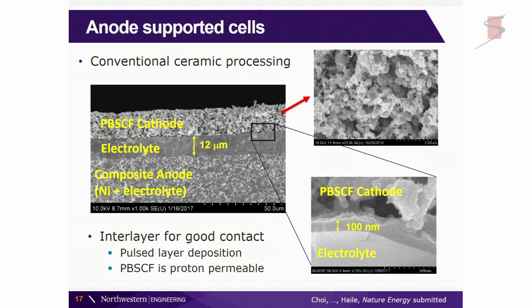And then because we were very concerned about good contact, so we would not have high contact resistance, we deposited a very thin film of this same cathode material directly on the electrolyte so that the electrons and the protons could get through to this site and eliminate the contact resistance that we interpreted was the cause of the poor performance of all the prior literature fuel cells.